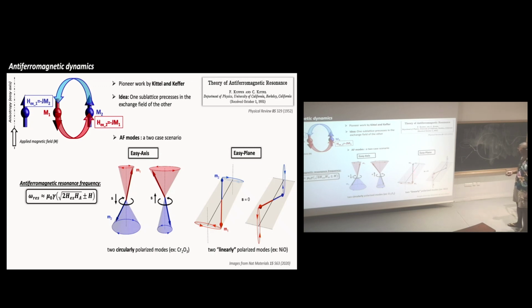So you have two modes. One which will preferentially rotate in the plane and one out of plane. That will make two modes which are at two different frequencies. This one will be a low frequency mode, and this one will be a high frequency mode. And I say linearly, but actually they are highly elliptical, with a ratio for NiO of something like 50 for one and 200 for the other. So this is why we call them linearly polarized.